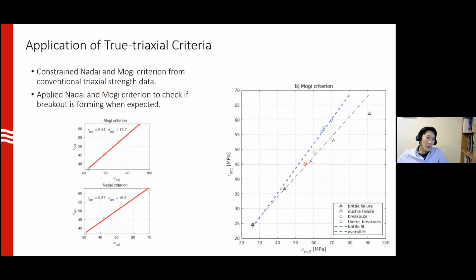So we did this approach. I won't get too much into the detail, but basically we have our laboratory data of strength from cylindrical samples that we tested in a conventional equipment. We can use this to constrain, for instance, a Nadai criterion or Mogi criterion. You can see that the fit to the data is quite good.